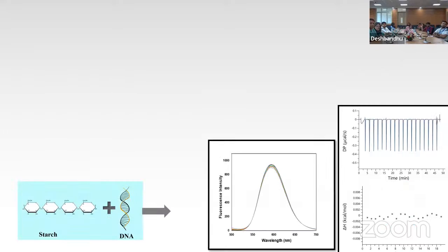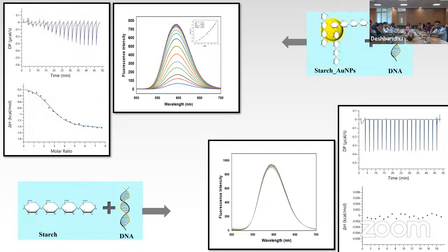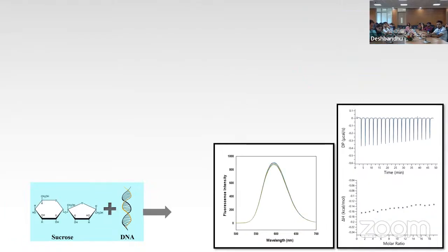Now moving towards the results, the interaction of pure starch was studied by ITC as well as fluorescence spectroscopy. No binding was observed from the ITC or the fluorescence spectroscopy. Whereas upon coating starch on the surface of gold nanoparticle, binding was shown. So we confirm that the coating on the surface of gold nanoparticle shows binding. Similarly, we performed similar studies for sucrose, pure fructose, and pure glucose, and binding was not observed. But with coating of glucose, sucrose, and fructose on the surface of gold nanoparticle, binding was shown.